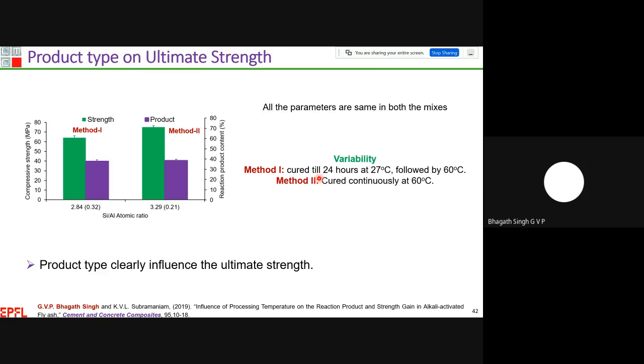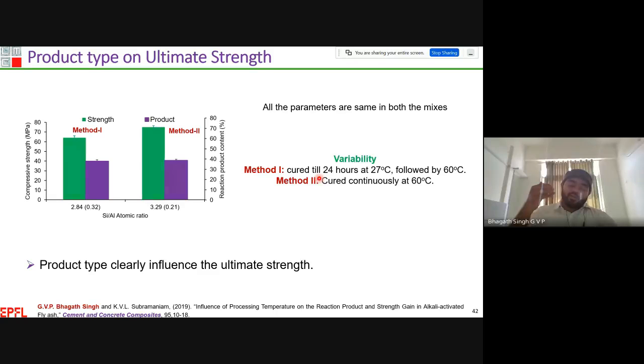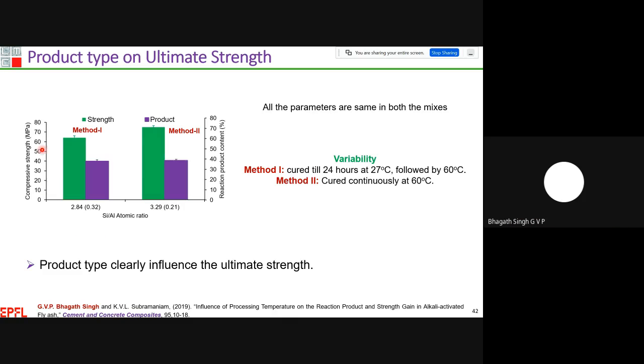Then I have determined the compressive strength at 28 days. I have determined the reaction product content, the silica to alumina atomic ratio, and also the unreacted fly ash content. The silica to alumina atomic ratio I have placed on the x-axis, and the left side of the y-axis represents the compressive strength, and the right side is the reaction product content.